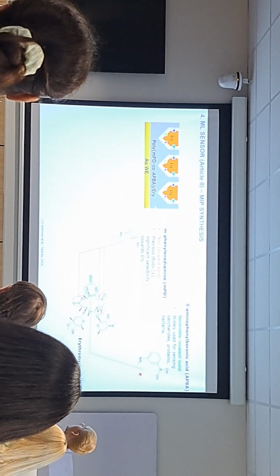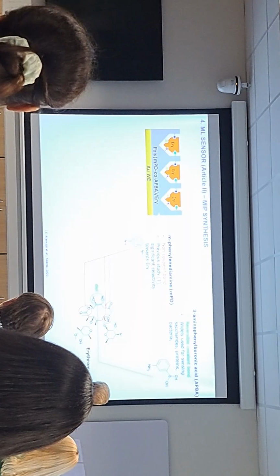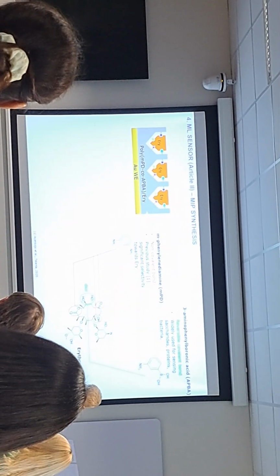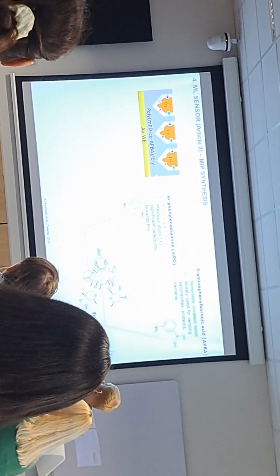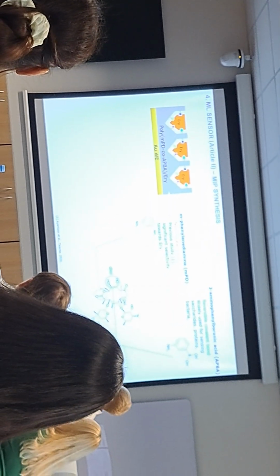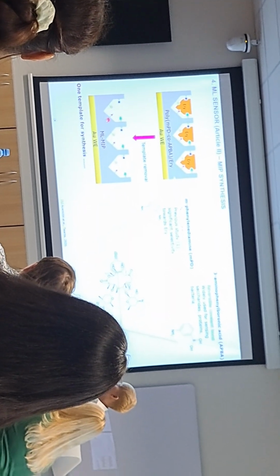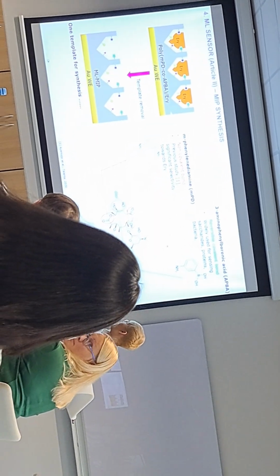Boronic acid is well known for reacting with something that has a diol, like glucose and so on, because in basic or neutral environment they can form a bond. If I put the system inside acid, this bond will be free. So it is just nice if I wash out this material using acid, and so I will have a material where all the binding sites will be free here. And of course the theory is that similar molecules in this way can go inside the cavity here, while non-targets are different in shape and so on.